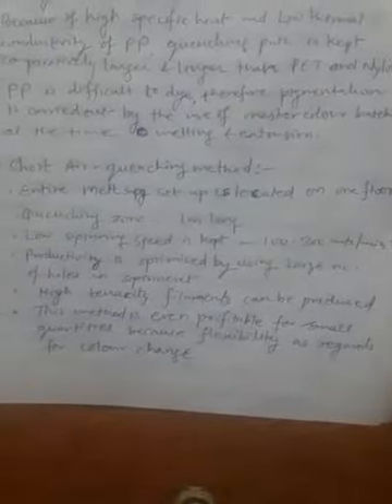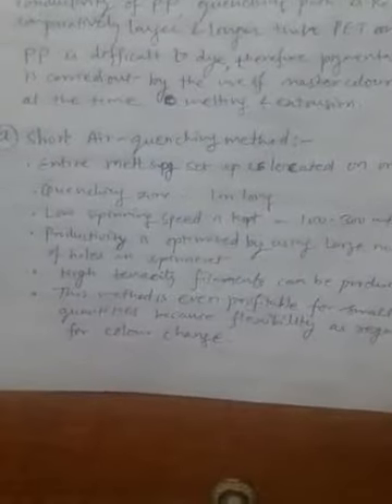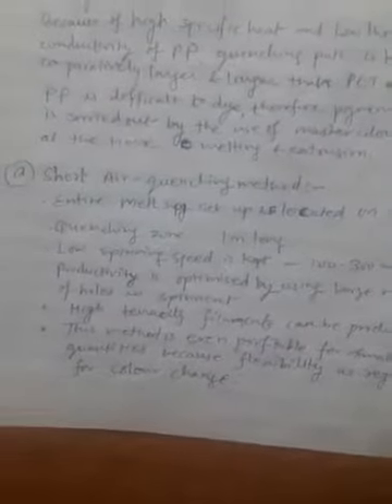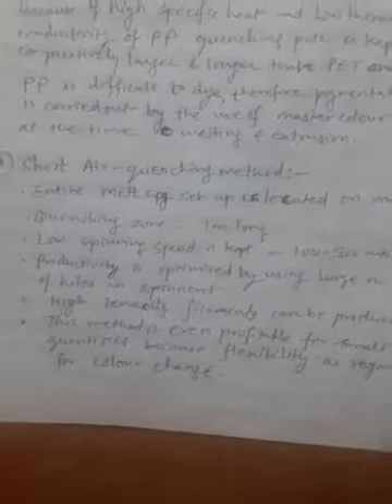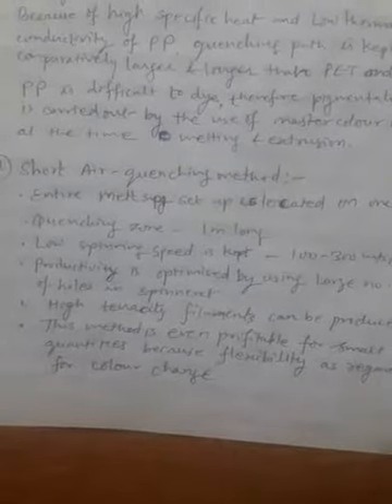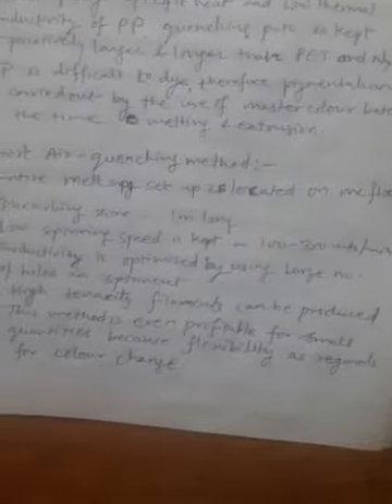One type of spinning method is the short air quenching method. In this particular method, the entire melt spinning setup is located on one floor only, not a very high floor, and the quenching zone is just 1 meter long. Therefore, because of high specific heat and low thermal conductivity, the spinning speed is reduced. A limited spinning speed is used, around 100 to 300 meters per minute for the short air quenching system.